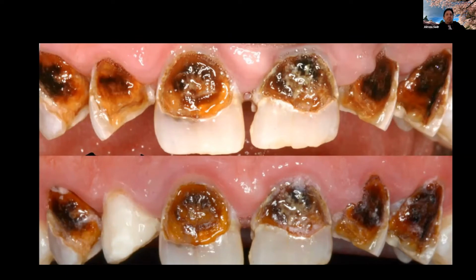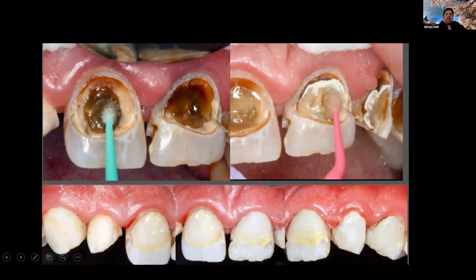We just took a manual instrument, cleaned up the edges a little bit with a round burr, and we went ahead and applied our silver diamine fluoride. And because I said silver diamine fluoride results in discoloration of the dentin, we also followed this application by potassium iodide. And let me talk a little bit about potassium iodide, because this case was basically a report on the potential advantage of using potassium iodide following the silver diamine fluoride. And then replace glass ionomer, let the patient go.